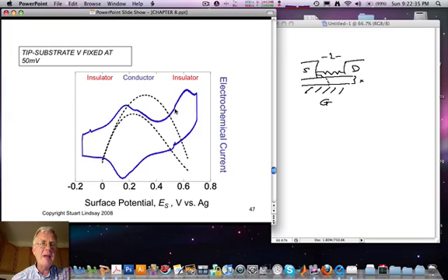The current rises again as one reaches this second oxidation of the oligoaniline. Then on returning the sweep, you'll notice the second oxidation is not reversible, but the first oxidation is. So experiments are confined to this region here, containing just this first reversible oxidation.